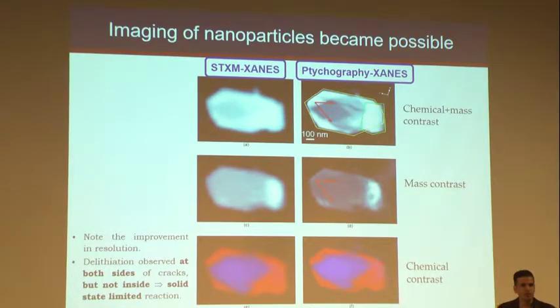In this particular case, we were fortunate enough to realize that this crystal had a fracture line. You can see it here in the mass contrast, a little easier to see in here. There's actually 2 of them. And when we looked at the chemical map, what the high spatial resolution of ptychography told us was that at both sides of that fracture line, if you look down here, it's a little blurry on the screen, but you can see it better on the screen down here. At both sides of that fracture line, there were domains of delithiation. At that fracture line, it was still pretty much iron 2.